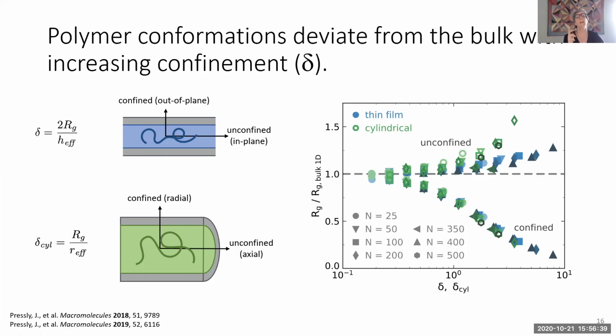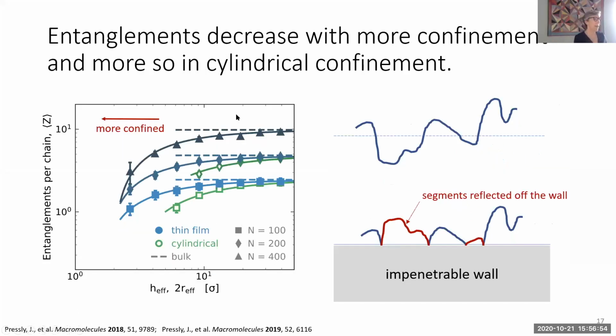Now, the reason the chain conformations are important as we think about dynamics is that the chain conformations tell us how many entanglements there are. So here we're looking at the entanglements per chain as a function of the thickness of the thin film or the diameter of the cylinder. And when there is very little confinement, so we're way out here at the end, you can see it's very close to the bulk. The bulk are the dashed lines. And as we squeeze the thin film down, we can see that the number of entanglements decreases. And that's true if it's a thin film or a cylinder.